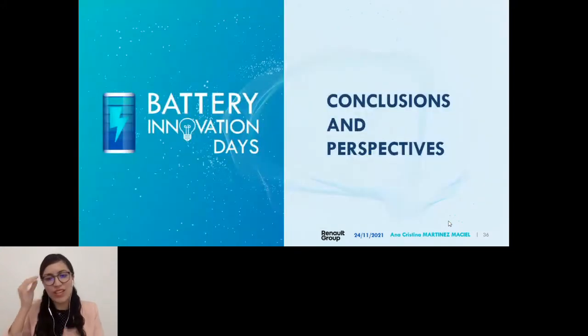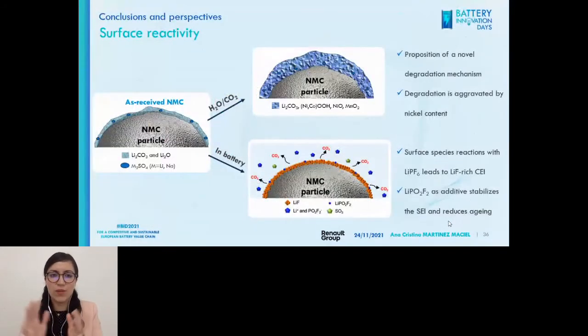So to conclude and give some perspectives on my work, let's come back to the surface reactivity study. The received materials, upon air exposure, produced hydroxides, oxides, and carbonates on the surface. We proposed a degradation mechanism for this, and under battery conditions, we were able to see that the surface of the NMC materials also changes.